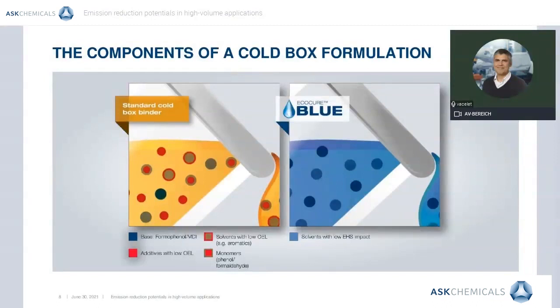In order to understand how to limit the emission by playing on the formulation, we prepared this illustration. It explains what can generally be found in Colbox resin. The active and essential products illustrated in blue, so the polymer and some low volatile solvents, are not directly harmful, while in red, we can find solvents and additives with very low regulatory exposure limits. Residual phenol and formaldehyde monomer are also particularly dangerous products. In the formulation of EcoCure Blue, in contrast, all these red products have been removed or at least used in concentrations below the declaration threshold, so that they are then considered as not relevant by the authorities.